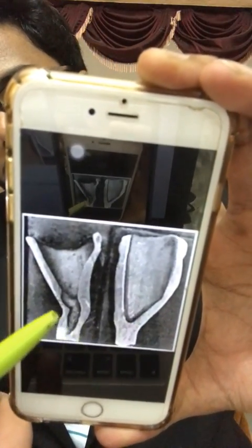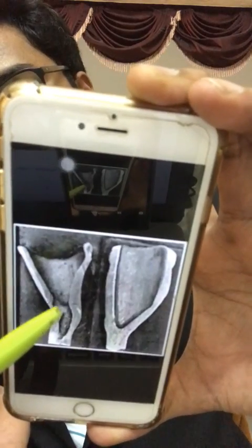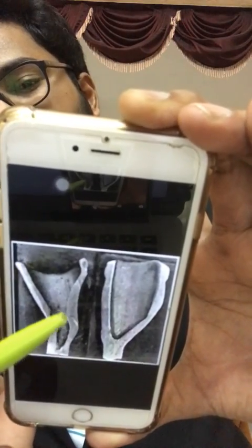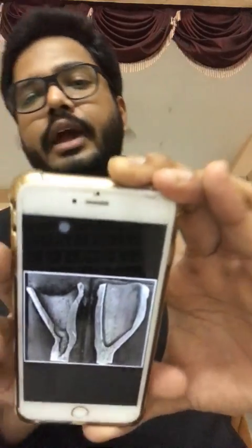So you can see here the difference, right? Almost at the incisoaxial line angle, at this point you have a suckback porosity. This is created because of the sprue attachment. Because of improper sprue attachment, there is impingement of molten alloy at this particular spot in a mold space, leading to creation of a hot spot, right? So that's the reason why that part has solidified last.